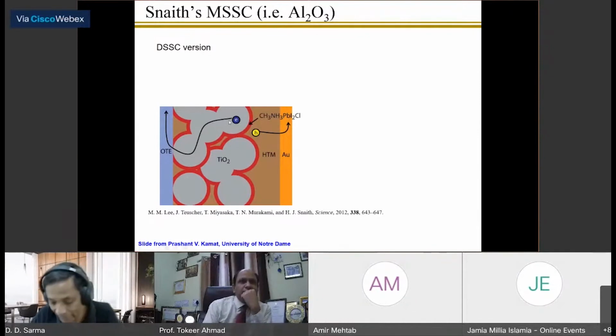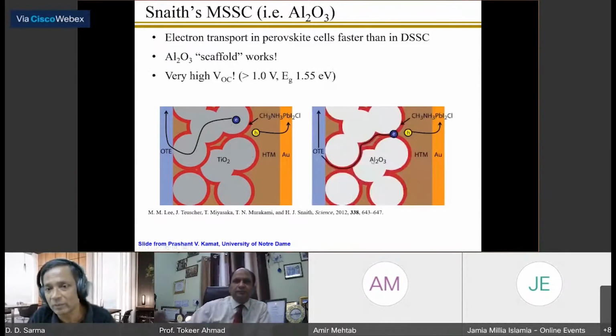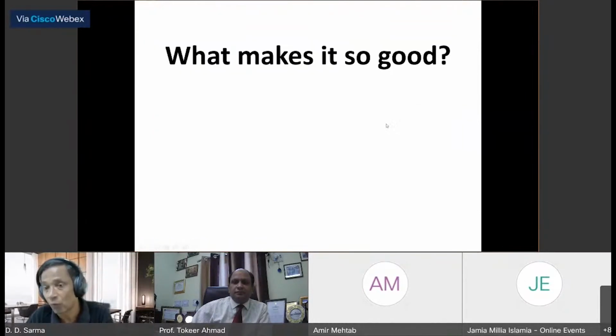But it turned out that this material did not need titanium dioxide, and this was proven by replacing titanium dioxide with aluminum oxide, which does not conduct electrons at all. And it was found that the efficiency didn't go down at all. So that got rid of these layers altogether, and it turns out that this material not only absorbs very well, but also has high mobility for electrons and holes. What makes it so good?